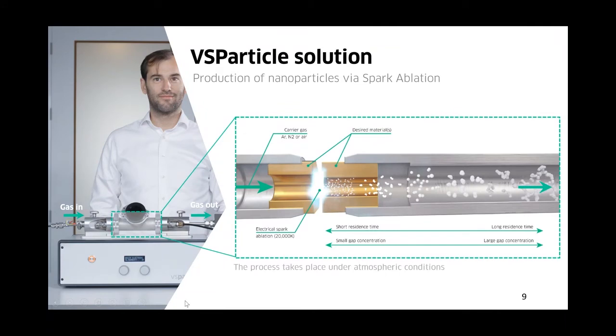If we zoom into the reactor head, we have our gas inlet on the left with our inert gas. Here we use hollow electrodes, and between these two electrodes a spark forms, producing a vapor of your desired material, which then agglomerates or aggregates to form larger clusters and larger primary particles, and then larger agglomerates and aggregates.